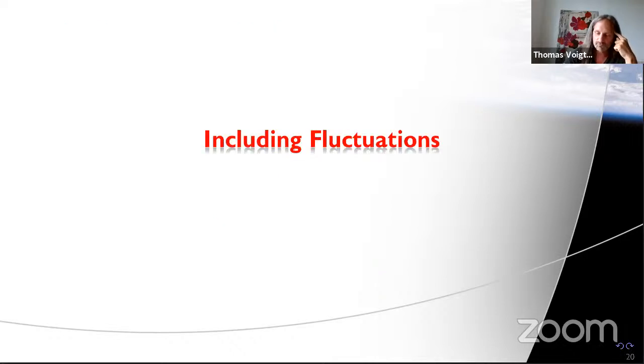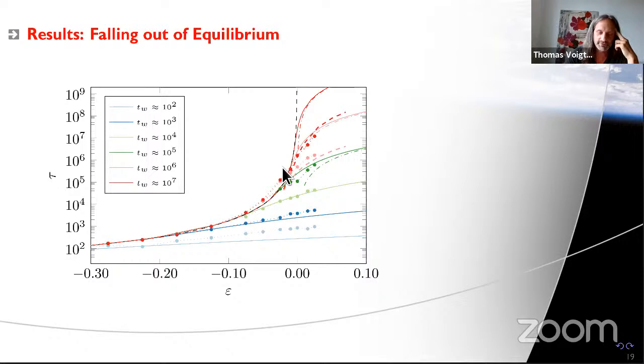And this is what I want to indicate rather briefly, because it covers an interesting point. I remember a fierce discussion that Magdaleno and I had, I think 3 years ago, when we had a small meeting also with Luis and Andreas Meyer. It concerns the question of whether the critical point of the non-equilibrium self-consistent generalized Langevin equation theory actually corresponds to the glass transition as measured by experimentalists, or whether it's still, as we know from mode coupling theory, a critical temperature or critical packing fraction that is unfortunately not the calorimetric glass transition.